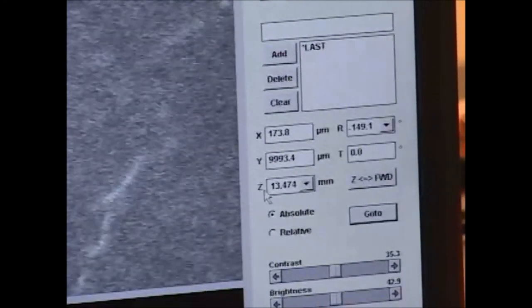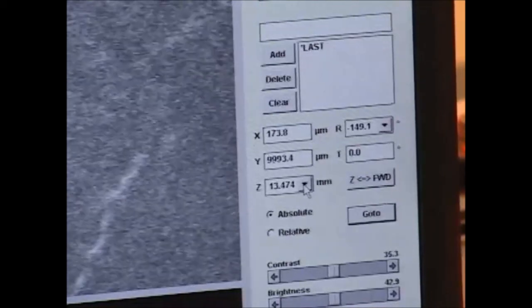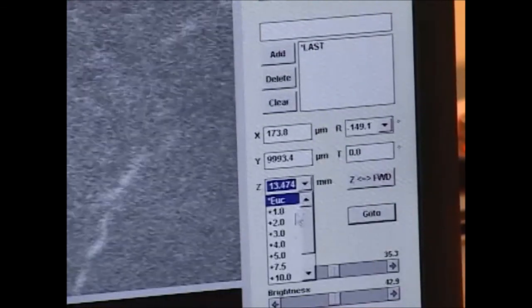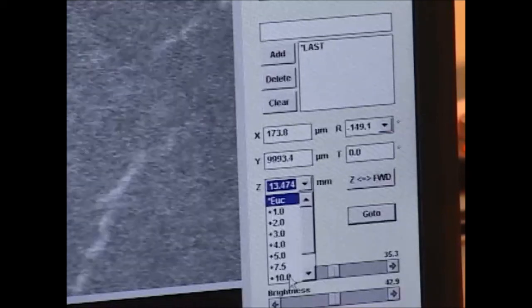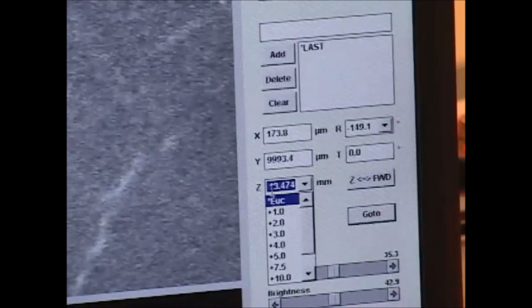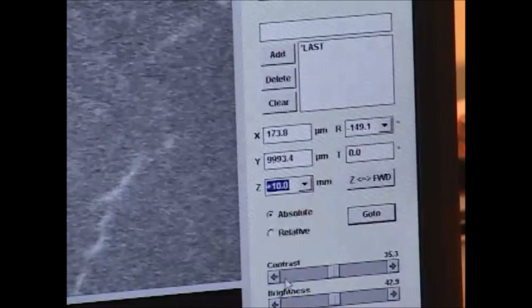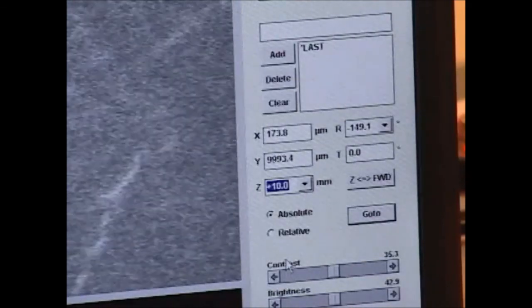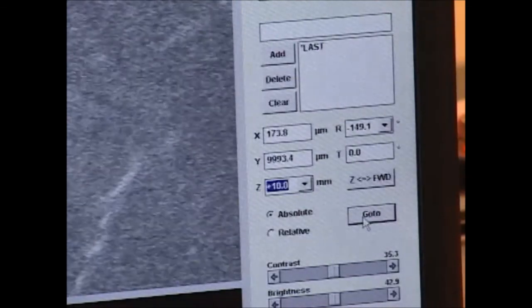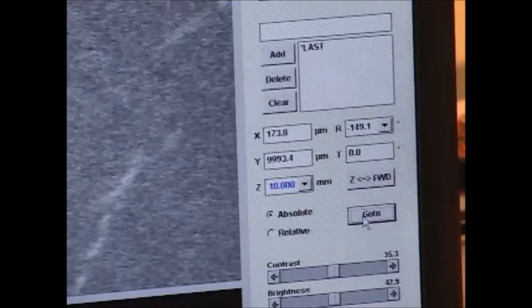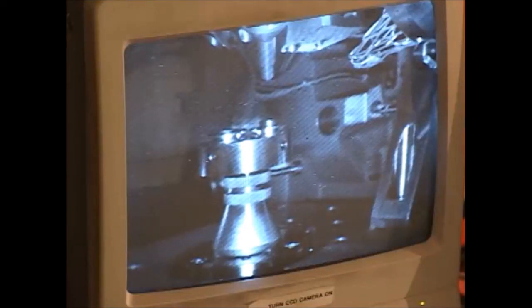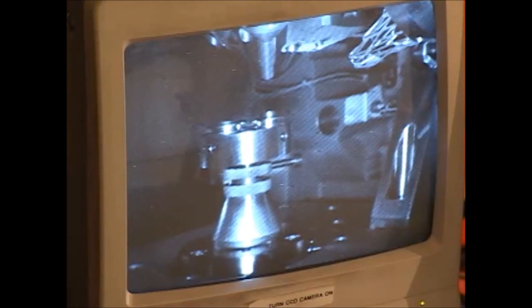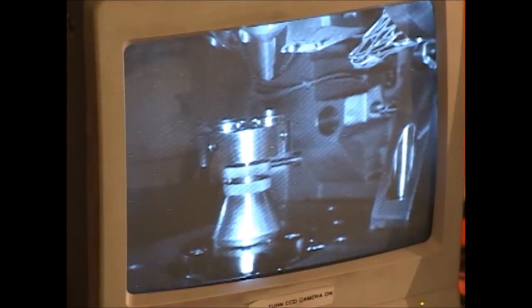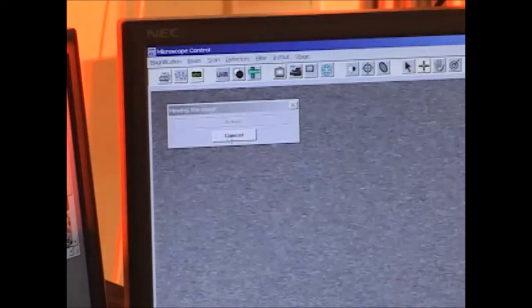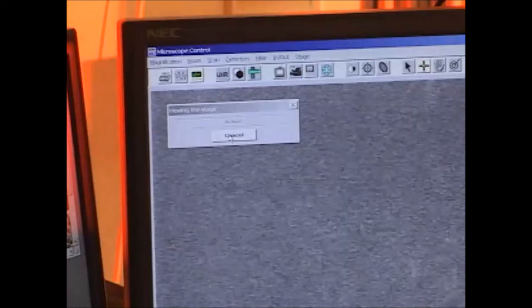So to adjust the stage height, I click on the drop-down menu in the Z field, and I select the final clearance that I want from the detector. Right now we're going from 13.4 to 10 millimeters. And then to initiate the move, I click on this Go To button. And I move the mouse to the upper left corner and watch on the CCD camera as the sample approaches the detector. If the sample gets too close to the detector, there's a cancel box that will open in the upper left corner, and I want to be ready to click on cancel so that the sample doesn't actually impact